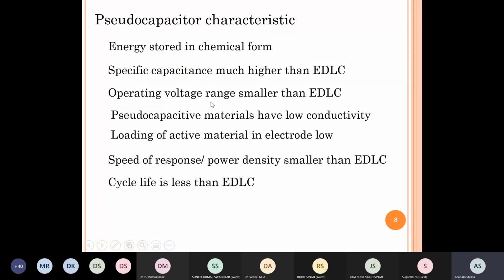However, the operating voltage range is much smaller than EDLC. So there are some advantages with pseudocapacitance, but it also comes with its own flip side. If you recall the energy equation, energy stored is CV squared, so if the voltage window goes down, it has a much stronger effect on the net energy stored. On top of that, most pseudocapacitive materials have low electronic conductivity. That also affects the performance of the device in a very negative way, because the device then starts to behave more like a resistor and less like a capacitor.